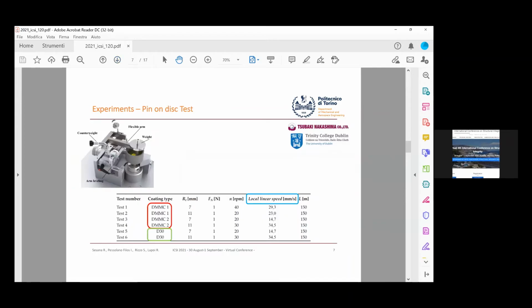Abrasion and friction measurements were carried out on pin-on-disc configuration by making use of the disc and bearings prepared as said before. Tests were performed by an Anton Paar TRB tribometer. The functional scheme and equipment that is compliant with the ASTM G99 and ASTM G130 standards is shown in the figure.